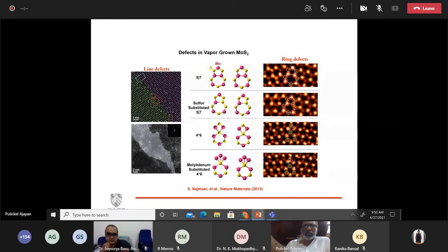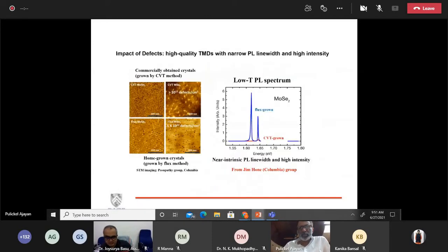And it's the same story with other 2D systems. Of course, something like molybdenum sulfide is not exactly a 2D layer because it has 3 layers, 1 of metal and 2 of sulfur. A single unit is essentially made of these 3 separate layers. And again, if you look at the grain boundary, you can find these defects like 5-membered and 7-membered rings. And they have their own local electronic structure and properties, which people are fascinated by.